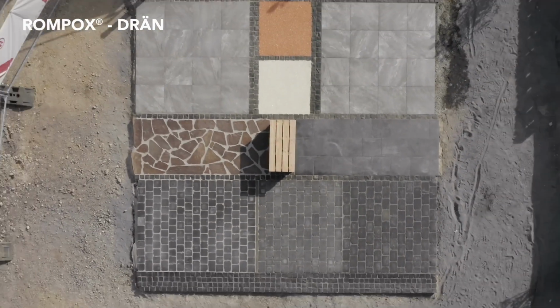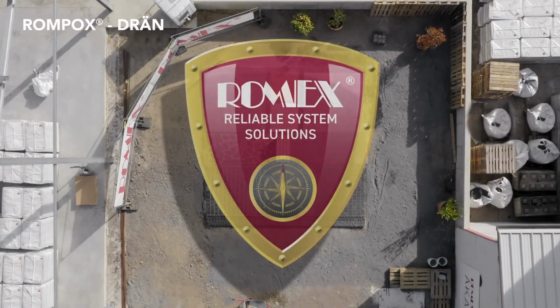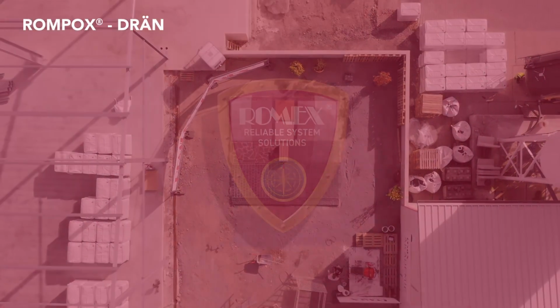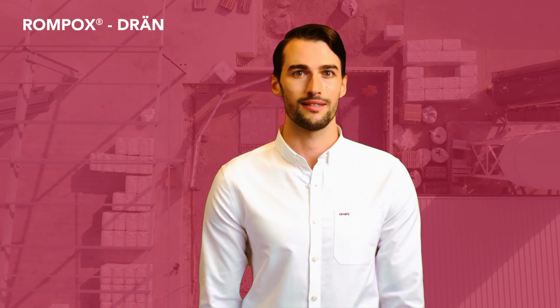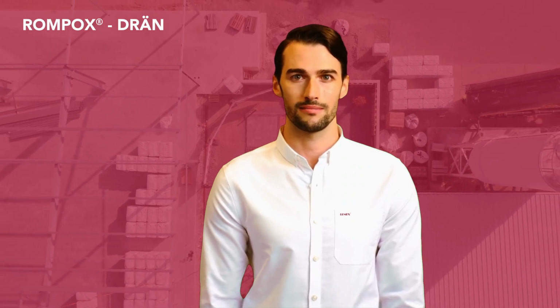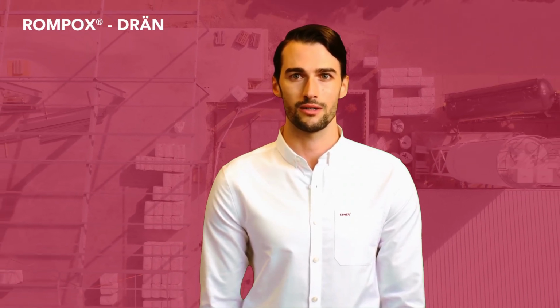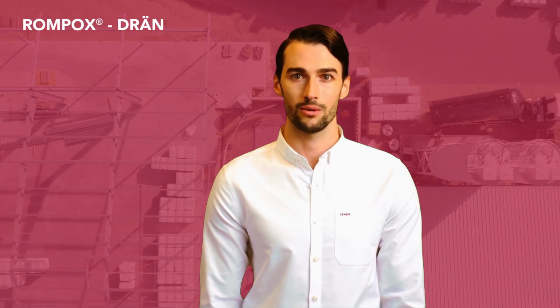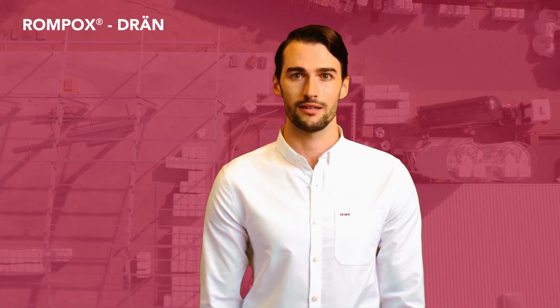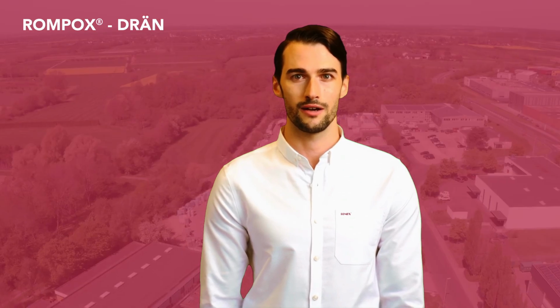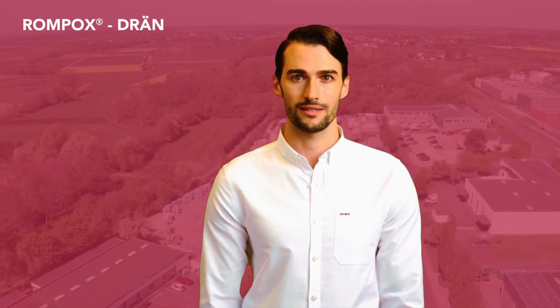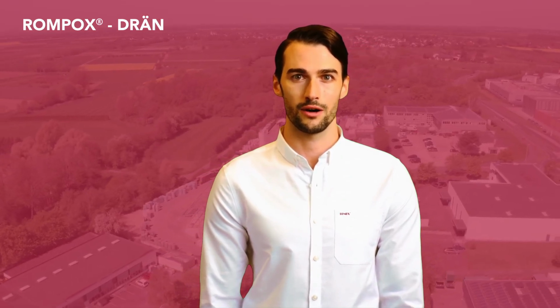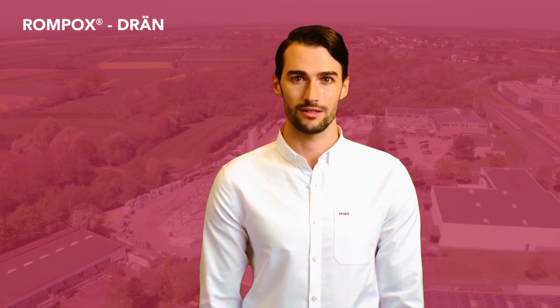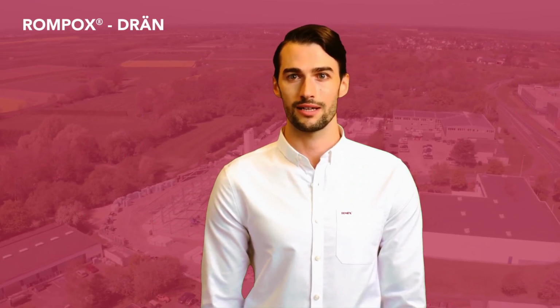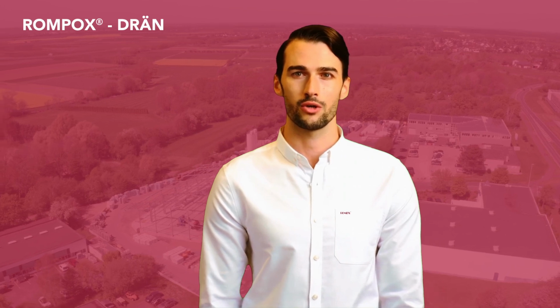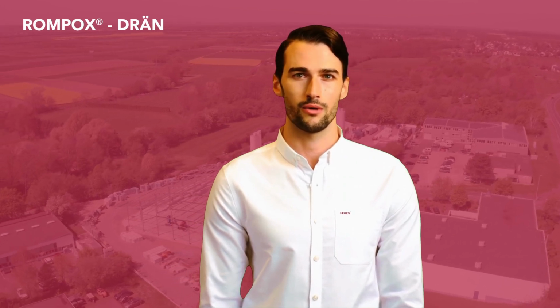It is therefore suitable for almost all coated and sensitive types of stone. Thanks to its compressive strength of more than 25 newtons per square millimeter, Drain is approved for use category N2. Furthermore, the mortar is frost and de-icing salt resistant as well as highly water permeable. Rompox Drain Grout, which has been available for over 35 years, thus meets all the requirements of modern synthetic resin jointing. A final note, Rompox Drain is best suited for tile coverings up to a maximum size of 40 by 40 centimeters. For jointing larger tiles, we recommend our product Rompox Ecofine.